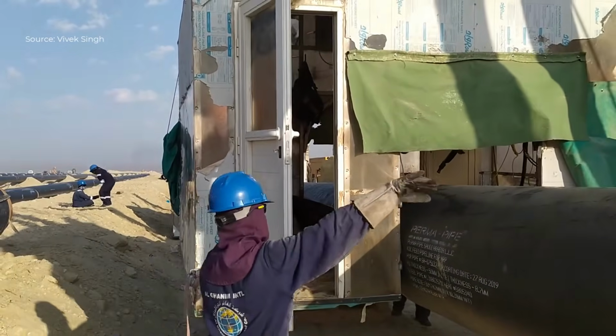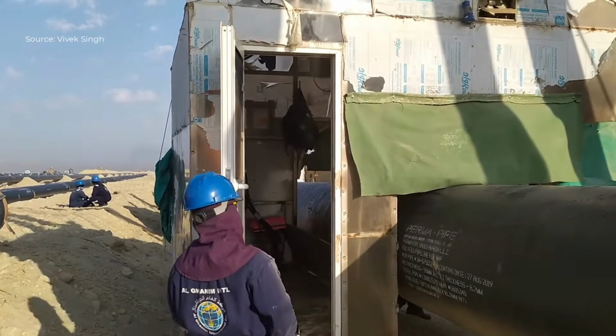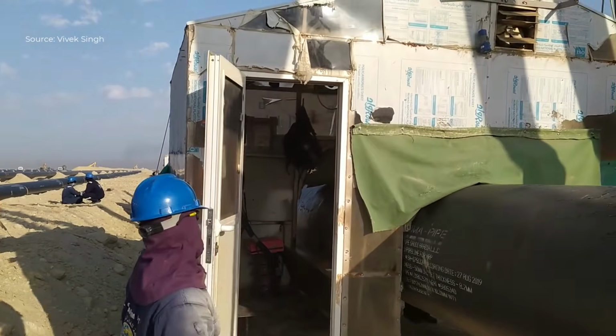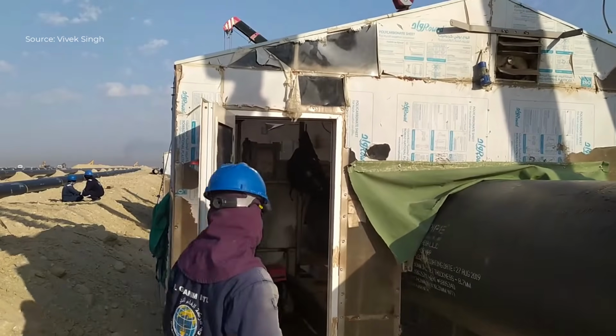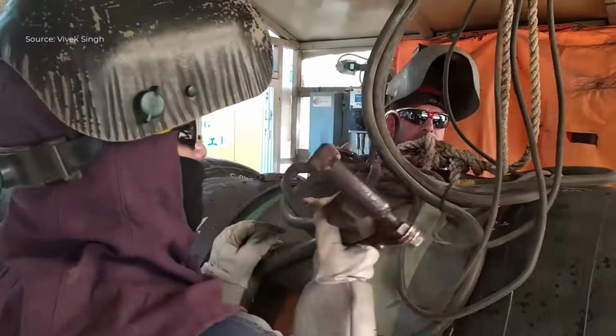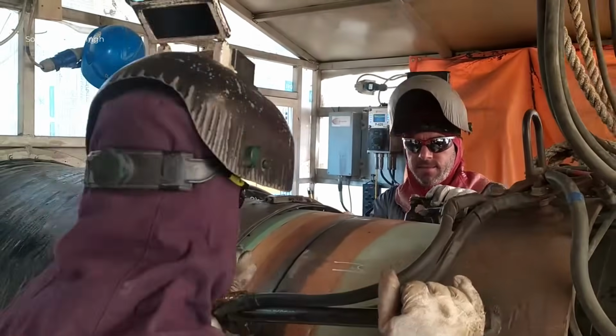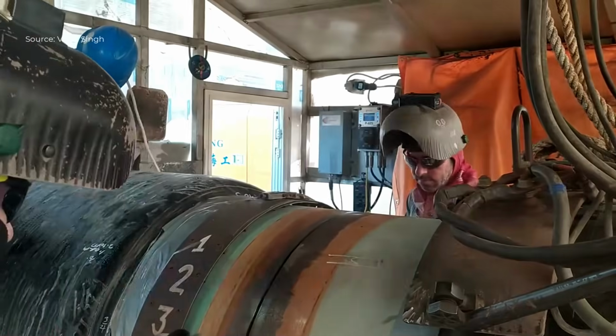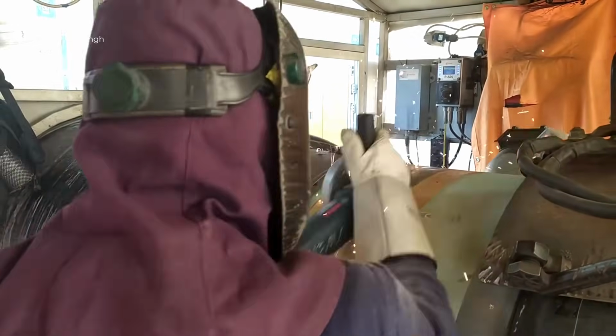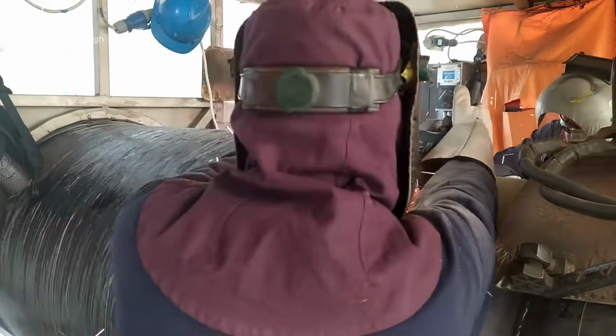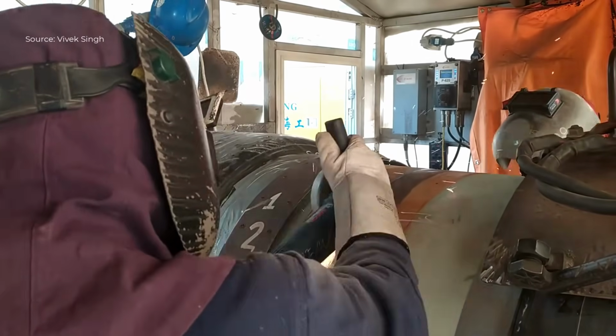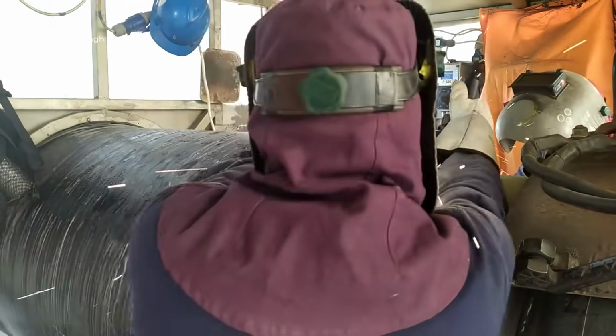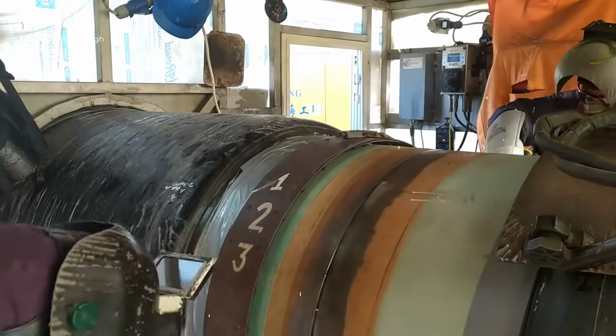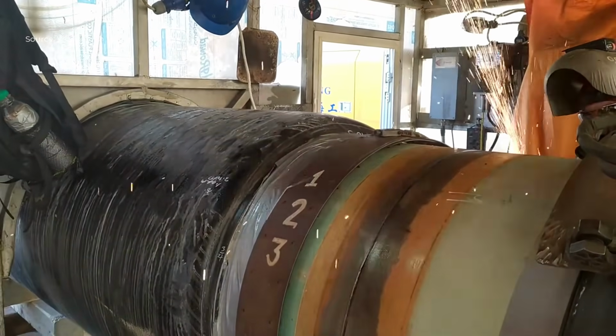The goal is not to remove the entire weld, but to create a uniform, clean profile that allows the automated torch to maintain a constant arc distance and stable heat input. The grinding also exposes fresh metal, eliminating surface contaminants that could lead to porosity or lack of fusion. Once the surface is visually inspected and confirmed to be smooth and continuous, the joint is ready for the high-precision automated welding stage.